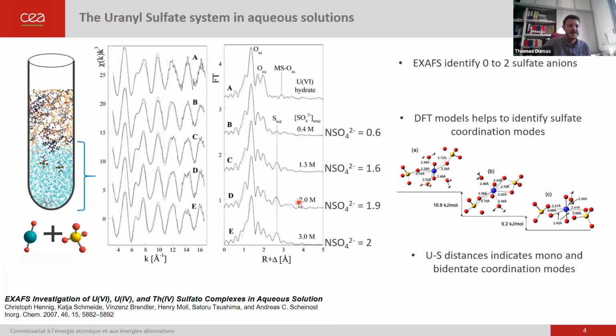For the aqueous phase, there is a nice publication specifically by Christoph Hennig, who is working at the ESRF, who some years ago published this data and showed that for uranyl sulfate complexes in aqueous solution, it's a convenient tool to identify uranyl sulfate complexes. And you see that you have between 0 and 2 sulfate anions around the uranyl. And also with the help of DFT models, he was able to show that you can discriminate between the monodentate or bidentate sulfate group coordination mode.